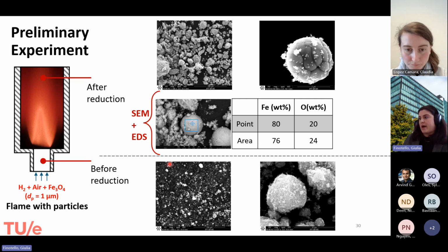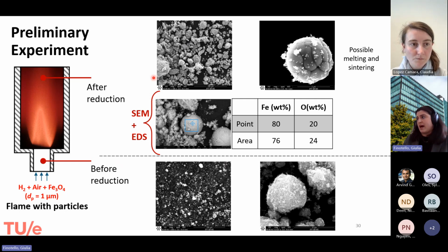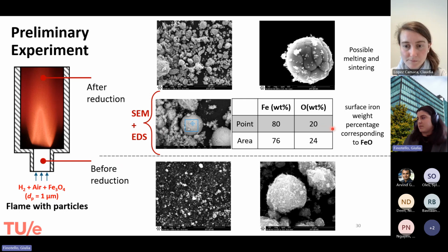And here you can see the powder before reduction. We have a relatively broad size distribution. And here you can see the powder after reduction. You can see already here that it has some melting, because you have very spherical particles, and you also see some sintering from these other SEM images. And we did also some EDS, where at the surface at least we could find some wustite percentage. So that means that there was some indication of a reduction. Of course, this is very, very preliminary. But that's indeed a sort of initial proof of concept for this very fast reduction process.